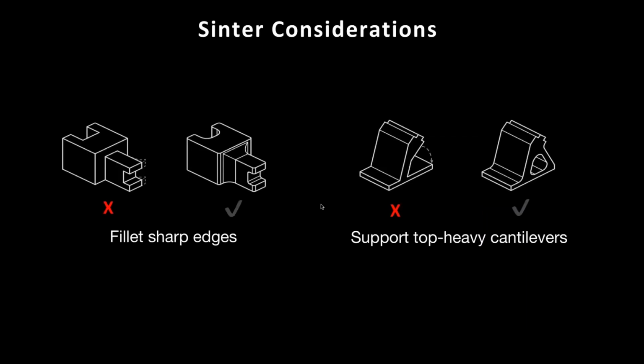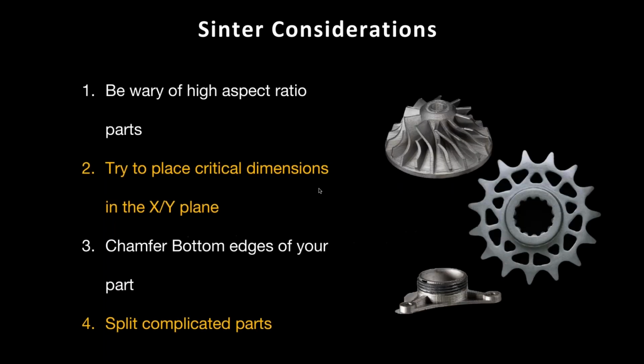All right, so design for sintering. Some of these considerations include filleting sharp edges. This can prevent warping. These sharp edges can act as stress concentrators, which can make your part not be completely accurate. And then also supporting top-heavy cantilevers. I was mentioning the high aspect ratio parts, and again, for some of these, more supports are necessary. So the part on the left with the X probably wouldn't sinter very well and may collapse because it is very top heavy. If you think about the heat and you have this metal sandcastle, it may fall apart if it's not supported correctly. So just adding in your own support, something like that, may help it sinter successfully. I'm going to keep reiterating it, but you just have to be wary of high aspect ratio parts.